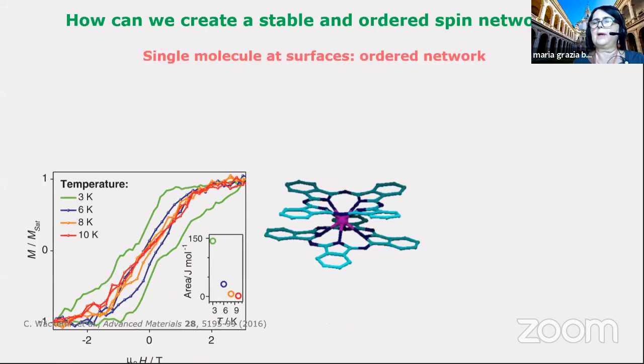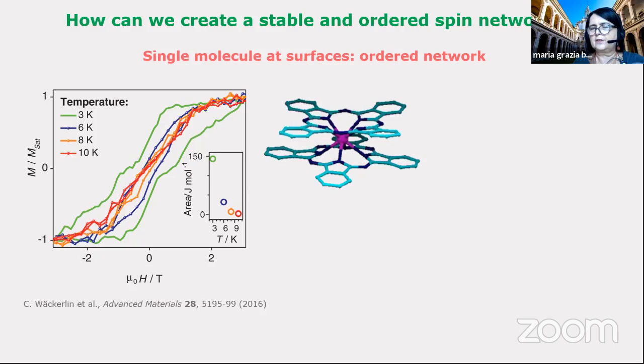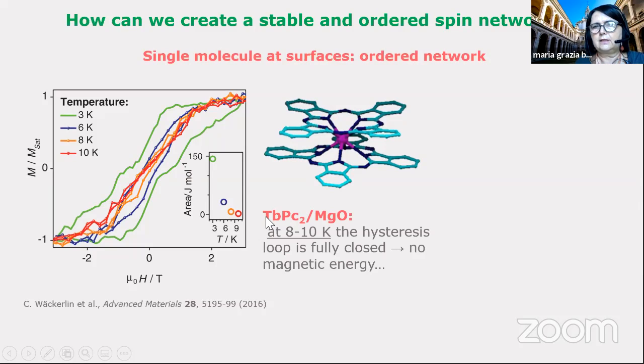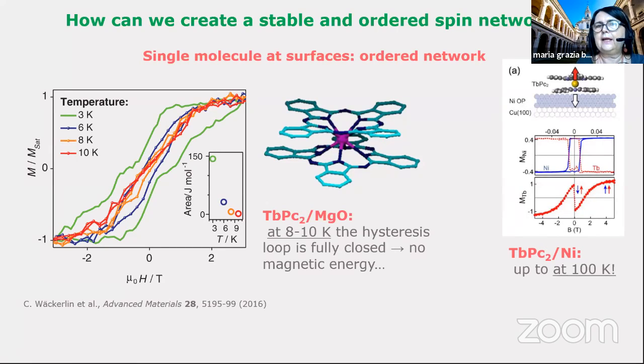So another possibility is to think about molecules, because with molecules, you can freeze the molecule on the surface if it is interacting with the surface, and then you can study the magnetic response of the atoms embedded in this organic cage. The organic cage, we expect, is inert from the magnetic point of view. And then when we study the hysteresis in this configuration, but also in this configuration, phthalocyanine on the same surface, we see the hysteresis, but the demagnetization exists at very low temperature, and if we increase the temperature to 10 Kelvin, the hysteresis loop is fully closed and there is no more magnetic energy. Then they tried to put the same molecule on a ferromagnetic substrate. And this was positive because in this configuration we have a remanence at higher temperature, but only up to 100 Kelvin, not at room temperature.